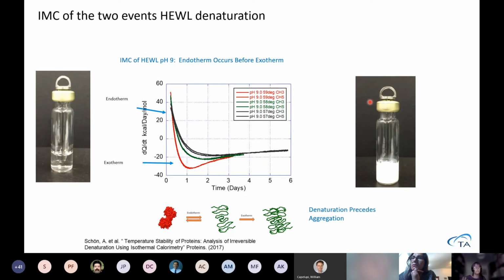We can see the denaturation is starting just slightly above 60 degrees. But even if you put them at temperatures below that, we can follow now we have an endotherm and an exotherm. So endotherm is the denaturation, exotherm is the aggregation. So we can follow that process. Now this has been measured for 6 days. This is how the formulation looks when it's put into the isothermal microcalorimeter. When we bring it out, everything has aggregated. So we can follow the process calorimetrically.